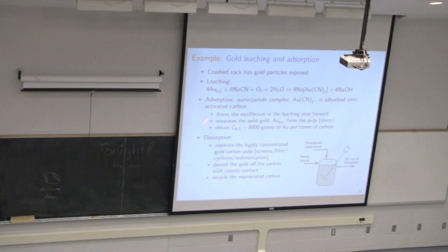So add some oxygen and slurry this up in water. You've got your water, oxygen bubbling, and then cyanide added in there. Keep it at a very high pH and you won't get any cyanide going into the vapor phase, and that's where your problems occur. So as long as you keep the pH high, you can work quite well with this, and you can move gold from the solid phase into the liquid phase. So when you get married and you get your gold ring, you don't put it in cyanide, it will disappear on you. So there's one way of doing it.